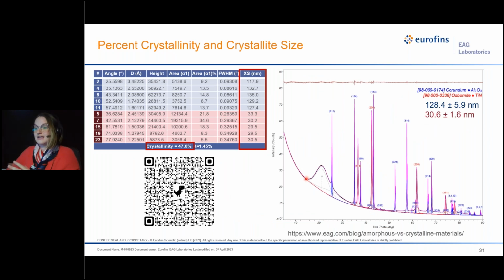This is the same data again, except this time I've profile fit. What that means is that I have an individual profile that's refined the shape of each peak, and we take the highest intensity, least overlapped peaks from each phase, and we can calculate that crystallite size, and then we average those and report it with the average and the standard deviation. So in terms of statistical analysis, that's what kind of statistics you're going to get on that. And the crystallinity of the sample is 47.0%, which means the program said this much is crystalline and this much is amorphous, so this percent has to be crystalline. And that's just a calculation that Jade can do for you.